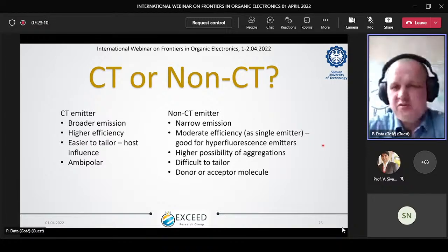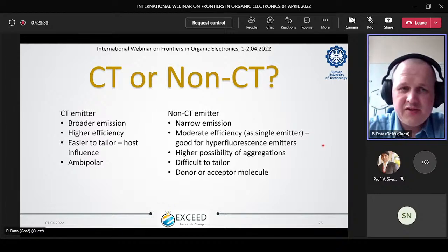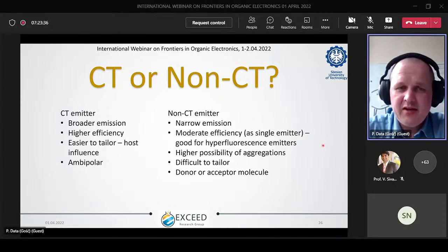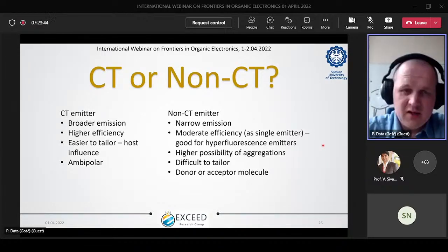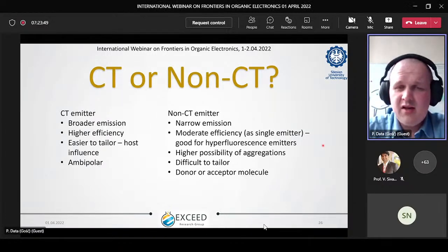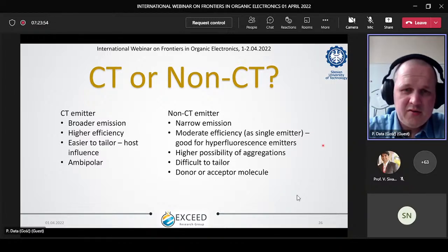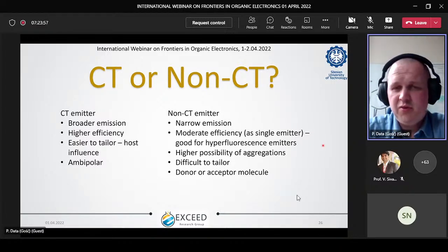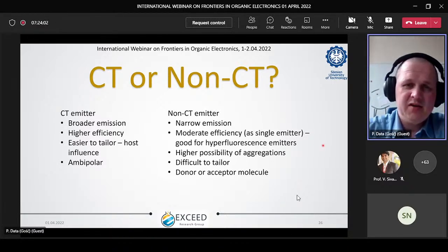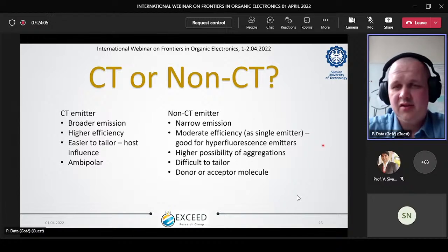Maybe I'll go a little bit further. CT or non-CT? Generally, it depends on your emitter. In the case of CT-based emitters, which I will show you later, we can tailor our emission. We can change our spectra by simply changing the host or slightly changing the conformation. Also, the CT emitters are ambipolar, which means they are easier to implement in OLEDs, because they can inject holes and electrons from the beginning.